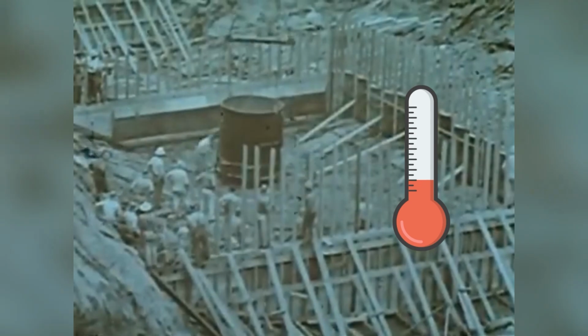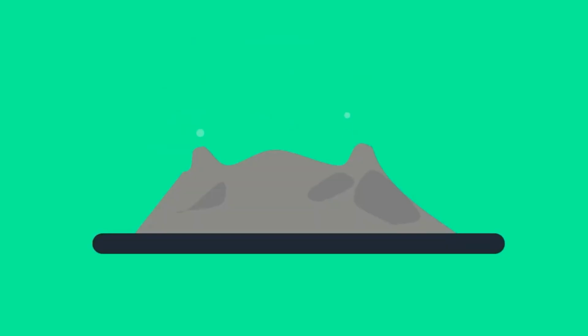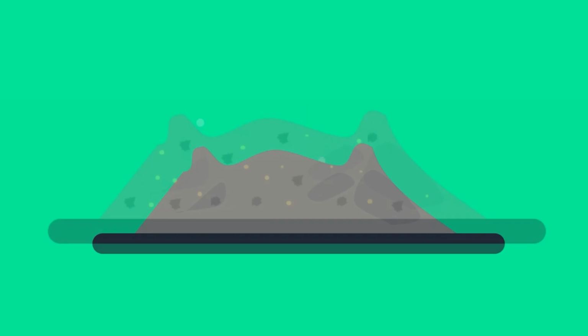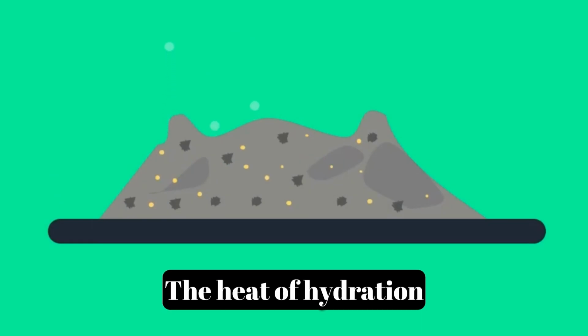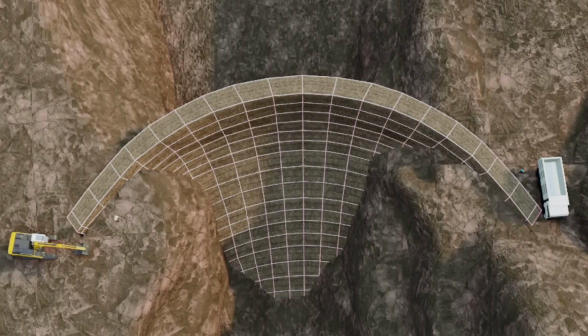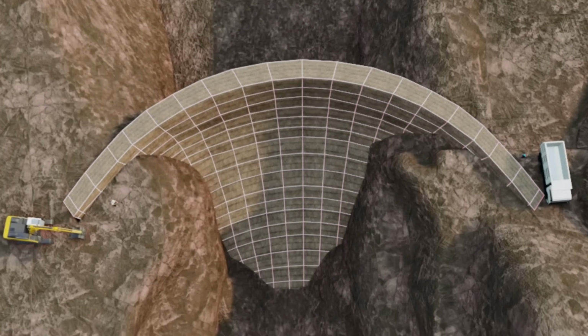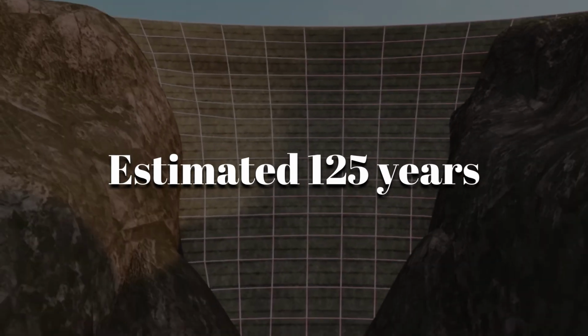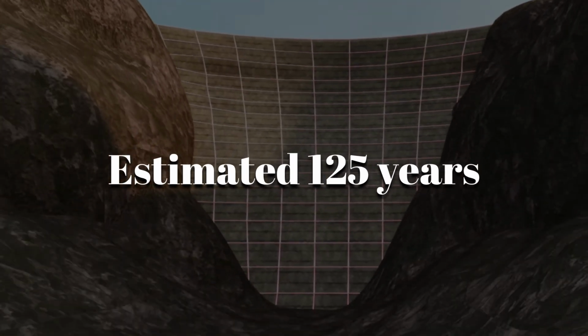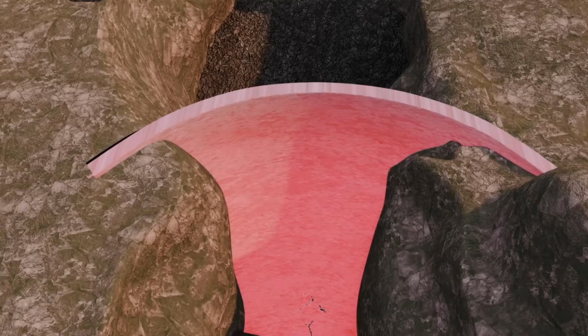One of the most mind-blowing challenges the engineers faced was managing the heat generated by the curing concrete. Here's the thing. Concrete generates a significant amount of heat as it hardens, a process called the heat of hydration. If the Hoover Dam had been poured as a single solid block, it would have taken an estimated 125 years to cool naturally. Not only that, but the intense heat buildup would have caused the concrete to crack and fail long before it ever became operational.